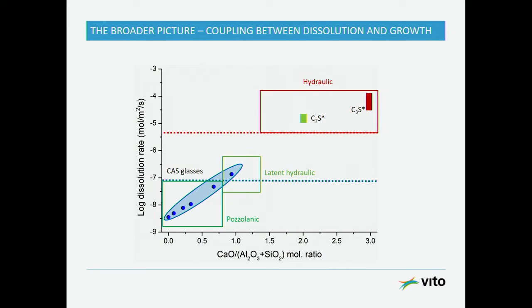So you have this coupling between what hydrates you form, what sets the concentrations in solution, the pH, the calcium, the aluminum concentrations, the silicon concentrations in solution, and their behavior in blended cements.